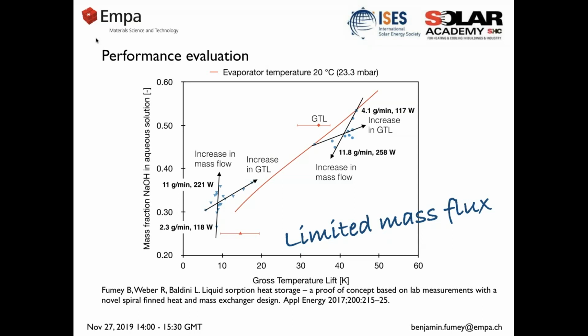So we do see in these tests now that we have a limitation in the mass uptake, and so a lot of our work now focuses on increasing the mass uptake while still having long exposure times and being close to equilibrium, which is a must for high energy densities.